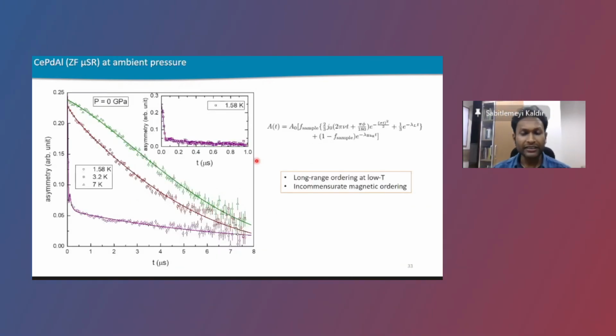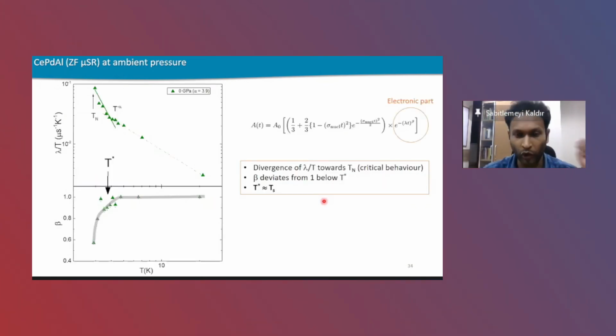Okay, so now let us discuss a little bit about the data on cerium palladium aluminum at ambient pressure and at zero field. As I told you, in the inset it is clearly shown that in the long range ordered state, it shows some oscillations. In order to deconvolute the spectra, we have used certain functions, and that tells you that there is an incommensurate magnetic ordering, and that is consistent with the neutron scattering experiments. Nothing that much important to say.